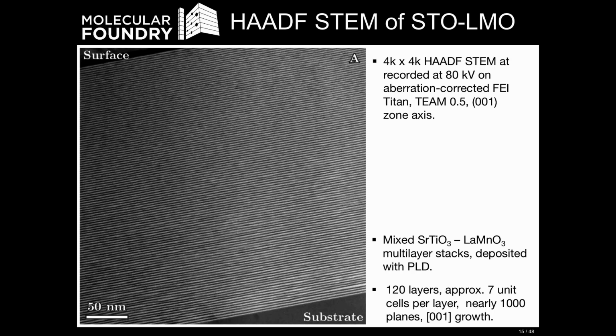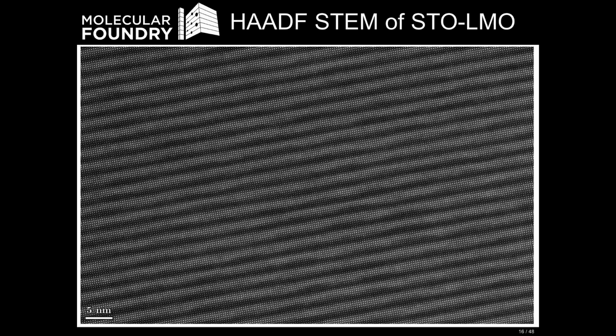In conventional imaging, if we record at very, very high resolution, we can form an atomic resolution image of the perovskite structure. If I zoom in, you can see a huge amount of information here. All of the atomic columns are resolved where the A sites and the B sites exist, but in between where the oxygens are, you can't see a lot of scattering, and that's because this is an annular dark field image. It captures only the highly scattered electrons. But interpreting this information is not trivial.